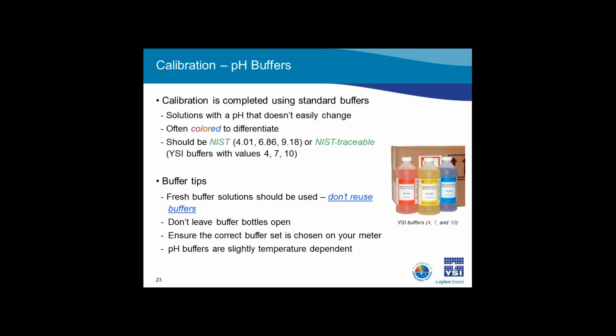Since transpiration or evaporation can affect buffers, make sure you close the bottles when you are done with them. If this becomes an issue, there are buffers available in larger airtight bags that will last longer. In order to avoid contaminating your buffers, make sure you thoroughly rinse your sensor with deionized water and blot dry with a chem wipe between calibration points. As a best practice in the lab, you should triple rinse with DI water between calibration points.